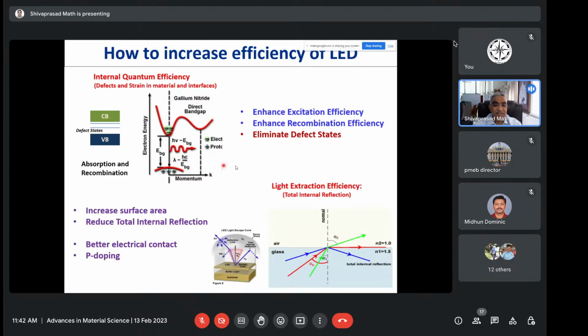This was not enough. There was another challenge in these materials. Gallium nitride has a very large refractive index, more than 3. That means most of the light which is produced inside will get totally reflected, and there's a huge reflection loss. The light doesn't come out. So this became a major problem with these materials. We had a material problem, the purity of the material, and the other was a geometric problem. How do I take on this challenge? So that's why we started.